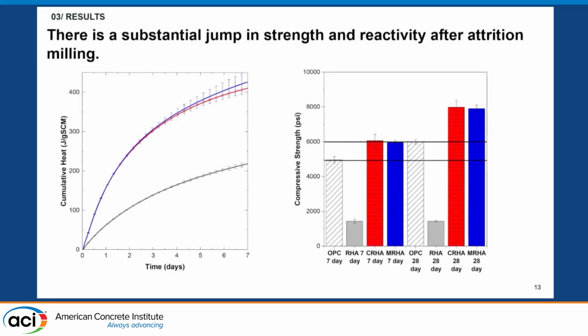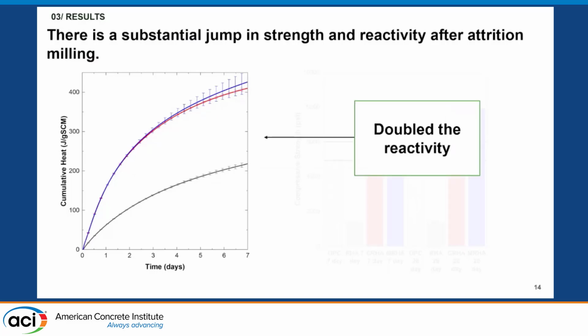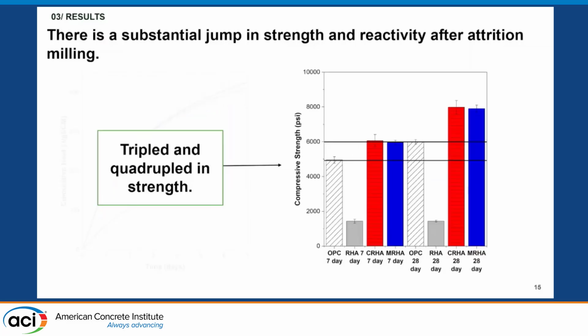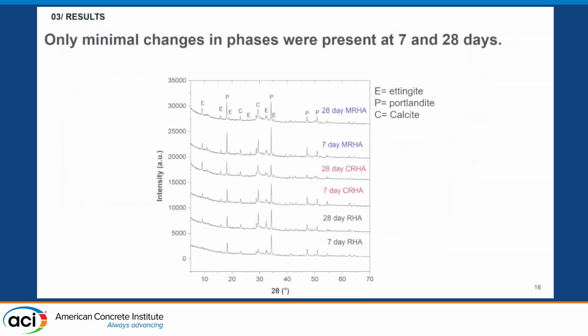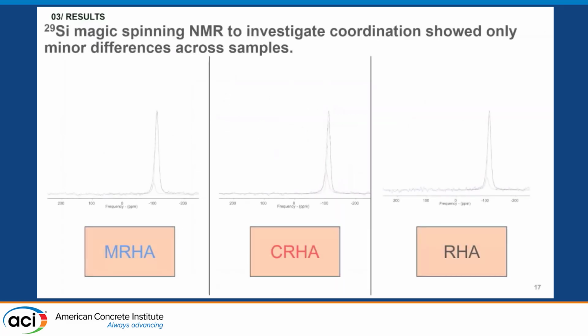And so what we found is there's that substantial jump in the strength and reactivity after attrition milling. As you can see there, there's that doubling in the reactivity from doing the R3 reactivity test. And then when looking at the compressive strength, there's a tripling and a quadrupling of strength in comparison to the untreated material. But there's only minimal changes in the phases present from the XRD.